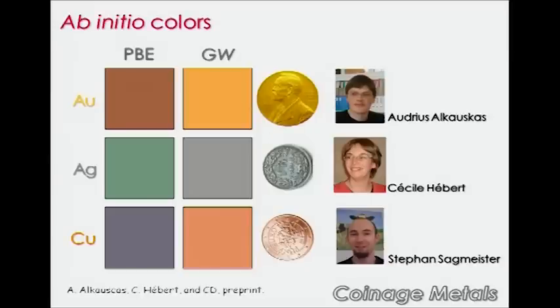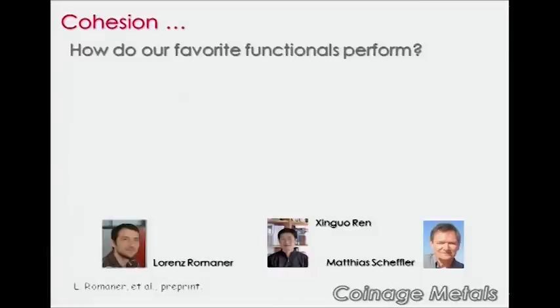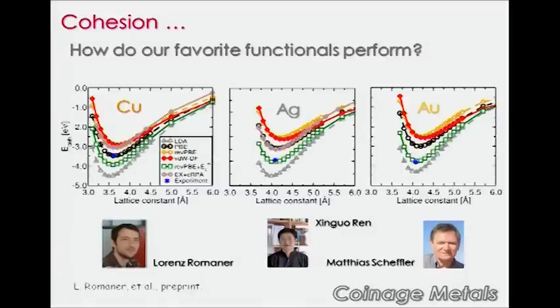Let's stay for 2 more minutes or so with copper, silver, and gold, the coinage metals, and go to those properties which are supposed to come out nicely from DFT, and which actually my title is about. So let's go to cohesion. How do our favorite functionals perform here? This is a very busy slide. It shows you the cohesive energy of copper, silver, and gold as a function of lattice parameter. And since PBE, for instance, is so well known for producing such nice lattice parameters, we have a look at the PBE results. So these are the curves which are given in black here. In fact, for all the 3 materials, you find that the minimum is very well captured at the experimental lattice parameter. This is true for copper, for silver, and for gold.